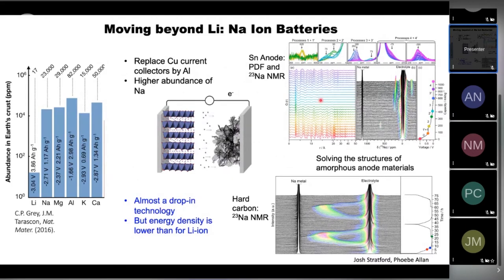We can also look at new materials for sodium batteries. And this is an example where we've used sodium NMR to look at the tin anode, to watch the different phases that are formed, and also used a second complementary technique, in this case, pair distribution function analysis, to look at the original tin structure, then transforming to an amorphous structure, and then transforming back to a crystalline structure. And by combining these two techniques, we were able to solve the structure of the different sodium tin phases that are formed.